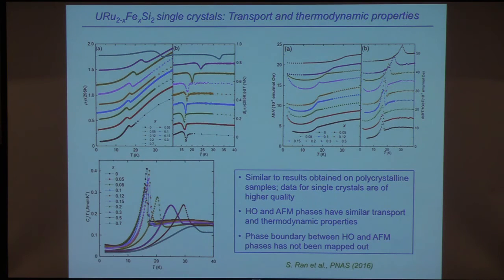And so, again, I'll go through this very quickly. Anyway, you make a lot of single crystals, you make a lot of measurements, and so these are various resistivity measurements at various iron concentrations. This is the derivative of these resistivity curves, and you can easily pick out the temperatures where you get the hidden order and large moment antiferromagnetic transitions.